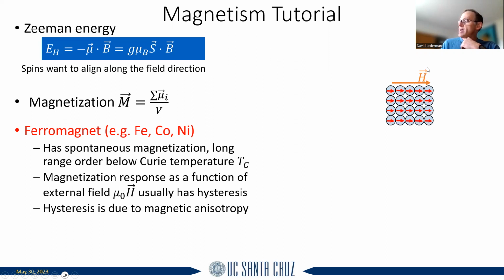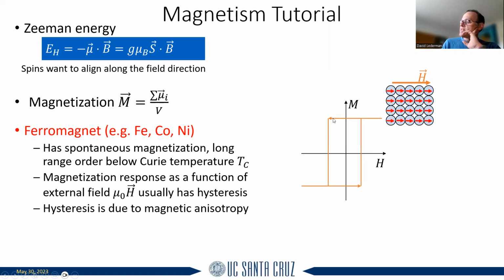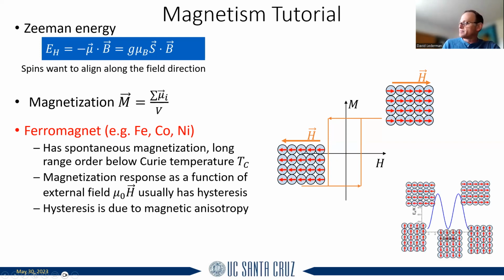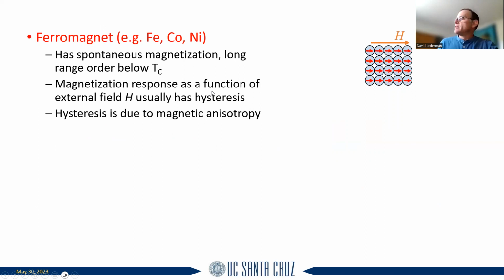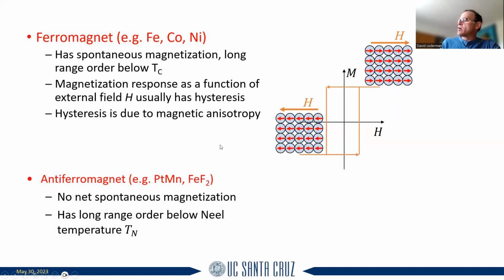So, for example, if you apply an external magnetic field H to the right here, and everything's aligned in this direction, and then you reverse the magnetic field, it takes a little bit of a negative magnetic field to actually reverse these spins, assuming that you have an anisotropy direction, for example, along this direction. And this is what it would look like. And then if you want to reverse it and go in this direction, then you actually have to apply a positive field to get these guys to overcome the energy barrier that I showed you before. Okay. So this is what we have for our ferromagnet.